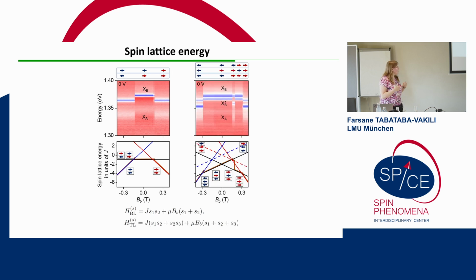Quite simple. Then in the trilayer, the two antiferromagnetic states are no longer energetically degenerate, and we have these additional two intermediate states here. So again, we start off in the ferromagnetic state here at a negative magnetic field. We transition to one of the antiferromagnetic states with just a spin of one layer flipping. Then at 0 Tesla, the other antiferromagnetic state would be energetically favorable. However, it would require the spins of all three layers to flip simultaneously. So this doesn't happen immediately. Instead, we continue along this curve until we cross one of these intermediate states and the other ferromagnetic state. And then with just the spin of a single layer flipping, we can transition to this kind of metastable intermediate state. And then with another 2 spin flips, we can relax down to the other antiferromagnetic state and ultimately to the other ferromagnetic state.